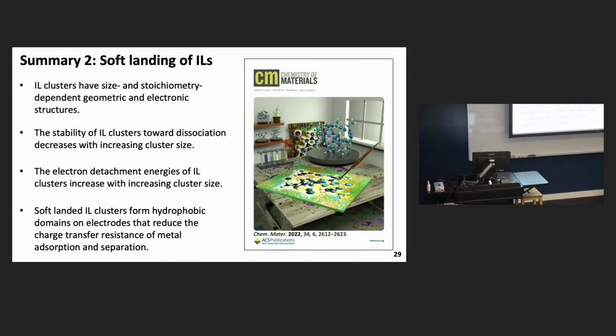So to summarize the section on ionic liquids, these have size and stoichiometry dependent properties that we can measure, both their stability and electronic structure. We find that the stability towards dissociation decreases with size, and the electron detachment energies increase with increasing size. And that soft-landed ions can be used to form hydrophobic domains on electrodes that reduce the charge transfer resistance involved in separating ions electrochemically.